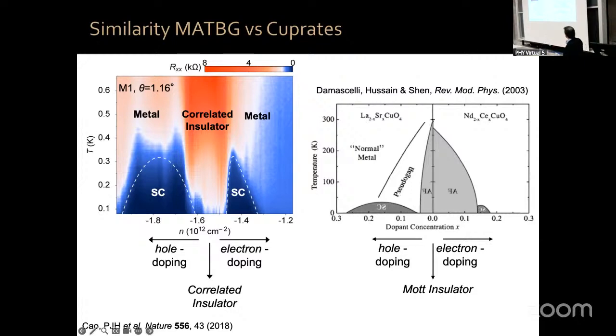In order to populate this with experimental data points, you have to grow hundreds of crystals with different chemical compositions, with different disorder realizations, usually using different materials types, because you cannot dope with electrons and holes over the entire range using the same type of material. This is done all in a single sample with a single disorder realization without chemical impurities. And we go from here to here, dial in a voltage knob, which takes a few seconds, okay? So obviously this is quite advantageous for many things.